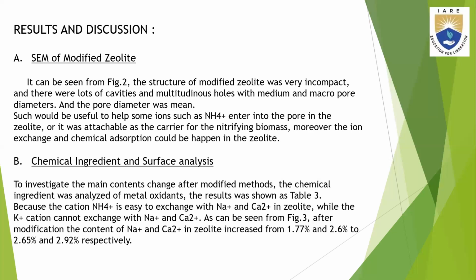After modification, the content of Na+ and Ca2+ in zeolite increased from 1.77% and 2.6% to 2.65% and 2.92% respectively.